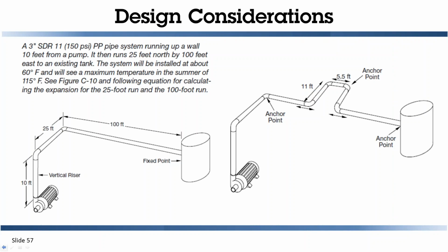Here's an application using 3-inch SDR11 pipe. With a 100-foot length of pipe, we need to consider the movement of that. So we can have an expansion loop in the middle there, 11 feet long, 5.5 feet wide, and that's going to allow the pipe not to see extra stress from the anchor points or put extra stress into that pipe joint at the tank.